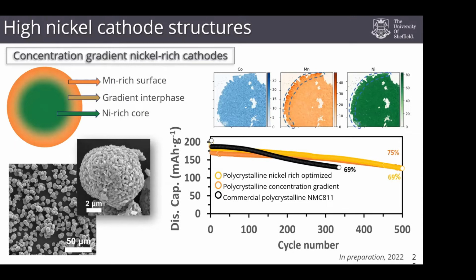We've been able to grow materials where in a single particle you have a nickel rich core and a manganese rich surface. It sounds a bit like box chocolates, with these centers that are really great, and then these protective outer casings. But that is essentially what we're doing. Why are we doing it like a gradient? Well, if we did it like a coating, you could potentially have an issue of delamination of your coating.